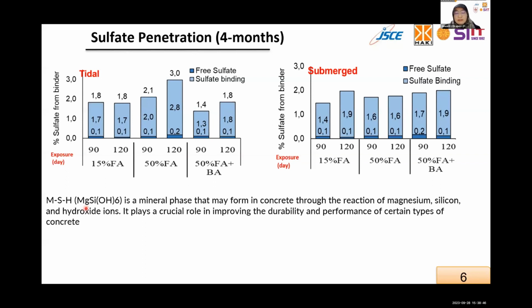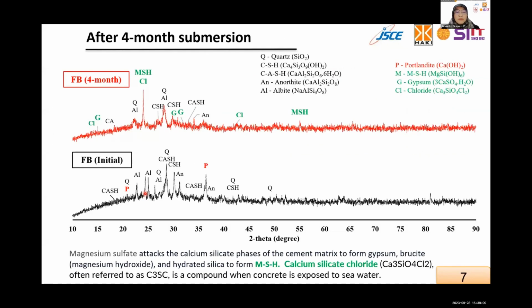It is particularly significant in concrete mixtures with a high content of SCM, like here we use more than 50% fly ash to replace cement, because this material provides a source of reactive silica and alumina, which can react with the magnesium ions to form MSH. And compare the concrete before, the black one, and after, the red one, after immersion for 4 months in the seawater. C3SC as a product of the chloride ion, this is Cl, and Cl here, was found, and the sulfate ion forms MSH and the gypsum. Here we can see that we find some gypsum here and magnesium silicate hydrate.